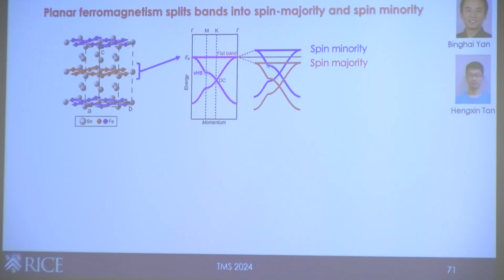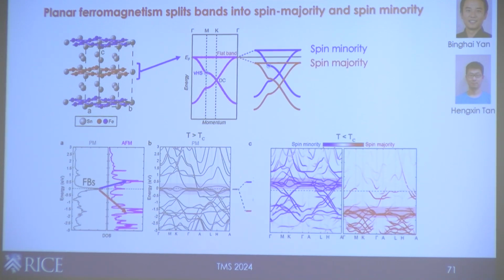So why can we even think about this picture for this material? We did some DFT collaboration with Binghai Yan's group, and essentially you can think about the expected electronic structure evolution. Each layer is ferromagnetic, which means that it should split into spin majority and spin minority bands. Indeed, this is what's qualitatively captured in the DFT. You can see that for the non-magnetic phase, the density of states has a large peak at the Fermi level, and that maps to the topological flat bands from the Kagome lattice. Then in the AFM phase, you have a splitting of this peak, which, if you look at the projected bands in the spin minority and spin majority states, correspond to the topological flat bands which are shifted up, and the ones that are shifted down, right?